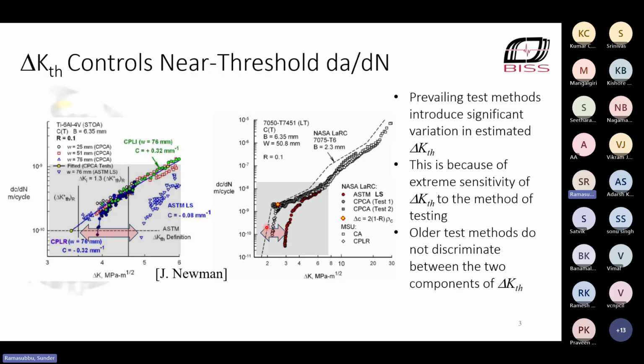But if you look at these two plots, and it would apply to most plots in the literature, there's a lot of scatter on the delta K threshold. That is the lowest delta K at which a crack will start growing, associated with 10 to the power of minus 7 millimeters per cycle. And that is because this property, delta K threshold, is very sensitive to how it is determined. You can't be comfortable with a property that depends on how you measure it. You want a consistent way of measuring it.